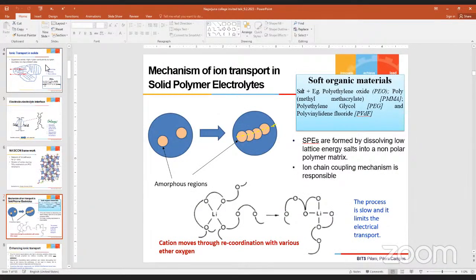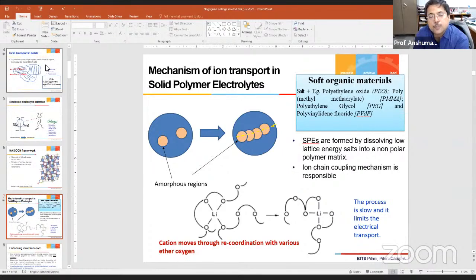All right. So another competitor, or one of the most important choices, you can say, where a solid-solid interface can be established is polymer. A lot of work on solid polymer electrolyte has been done by Professor Ravindra Gupta ji and of course Verma ji and Professor Agrawal's group. And solid polymer electrolyte still is one of the fascinating materials for the ionics community. And why it is an important choice is because if you talk about two contacts of solids, then polymer is the best choice to have a smooth contact at the interface. The polymer's contact with the solid can be the easiest and smoothest contact as far as solids are concerned. I'm not talking about the gel at the moment, only solid polymer electrolyte, which will be liquid free.